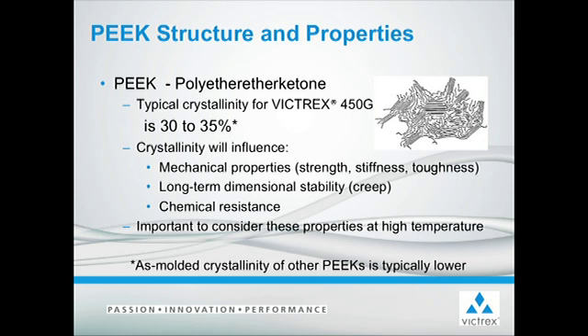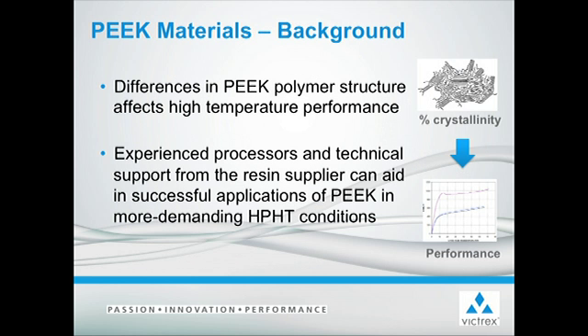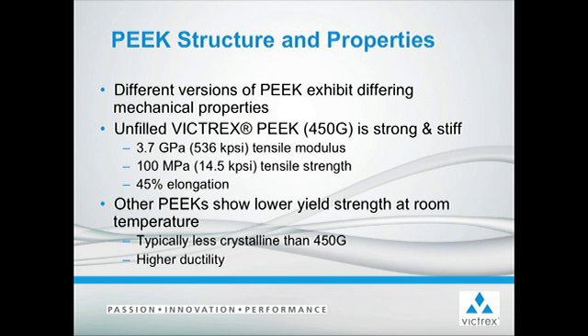This crystallinity influences properties like mechanical properties, including strength, stiffness, and toughness, long-term dimensional stability, like creep, and chemical resistance. It's also important to remember that crystallinity influences properties at elevated temperatures, even more so than at room temperature. Differences in the PEEK polymer structure, specifically the crystallinity, will affect the high temperature performance. Experienced processors and technical support from the resin supplier can help aid in successful applications of PEEK in more demanding HPHT conditions.